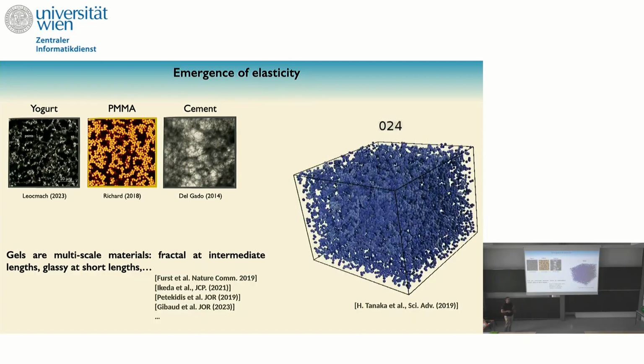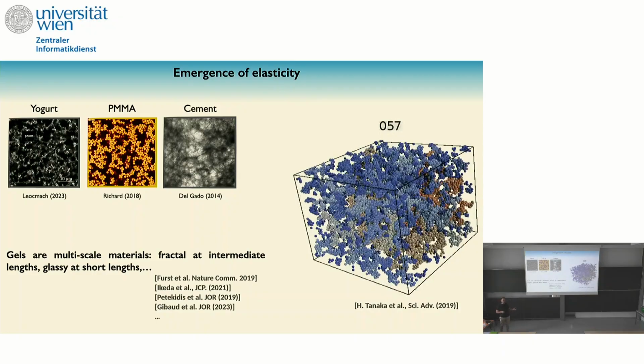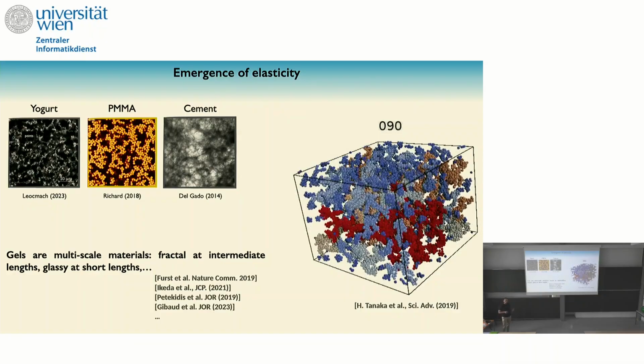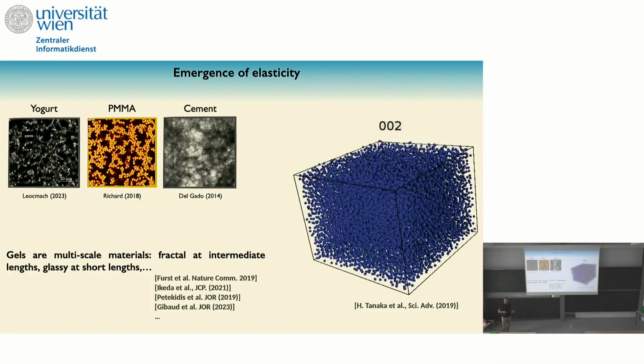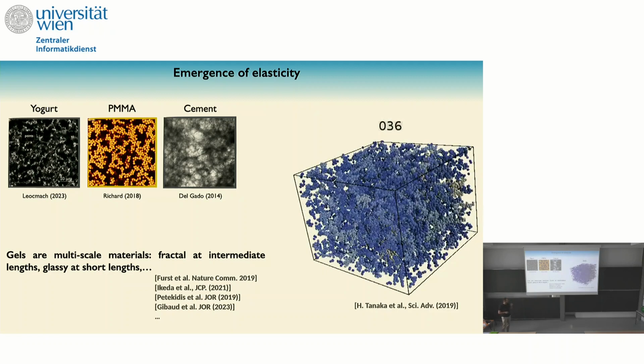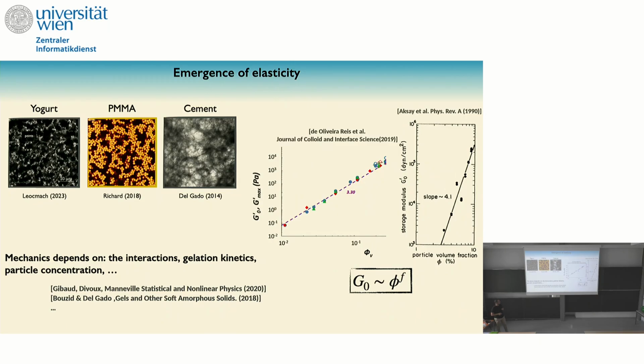So you have different types of length scales that emerge in this system, and that's what makes it a little bit complicated to understand why and how the system gets into a solid phase and how we can understand its elastic properties. Speaking of the elastic properties, if you measure the shear modulus at vanishing frequency as a function of the volume fraction, your control parameter, what you find is that the shear modulus scales with the volume fraction with some exponent f. And this exponent doesn't seem to be universal. If you plot it as a function of the volume fraction, you can get exponent 3, 2, 4, and even more than that.